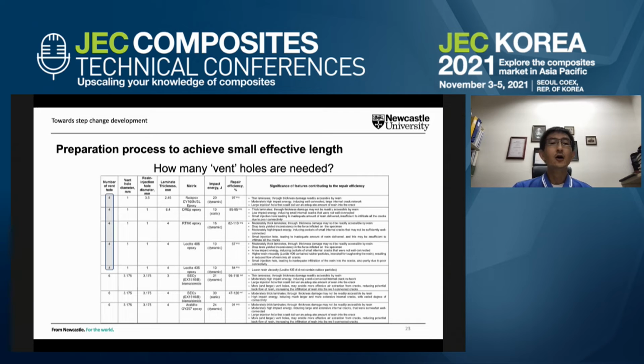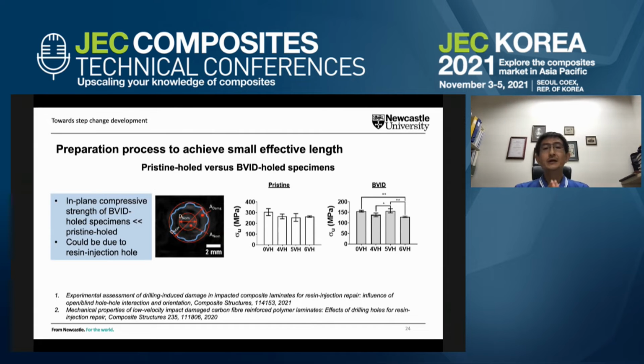And we also explore how many vent holes are needed. We find in the literature that there are a lot of studies ranging from 4 holes to 5 holes and 6 holes. But the repair efficiency results have been rather contentious in that there's no real trend as to what's the best number of holes. The repair efficiency could range from as low as 47% to even as high as 126%. So we carried out an extensive study to try and understand how the number of holes affects the mechanical property of the damaged laminate when you drill these holes into it. And so that enables us to optimize for the number of holes.